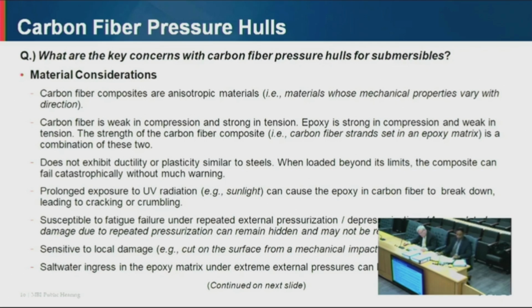So then the next thing is prolonged exposure to UV radiation can cause the epoxy to get damaged. Okay? So in some cases, you add something called a UV stabilizer. It's a chemical that's added in the epoxy, and that protects the epoxy from UV radiation. In some other cases, you can have a gel coat or a top coat which is placed on the epoxy. For example, you can have a polyurethane coating, and that protects the epoxy from the damage caused by UV radiation or the sunlight. Okay? So if you don't have this protection and you expose the carbon fiber composite to sunlight, the UV radiation will degrade the mechanical properties of the composite.